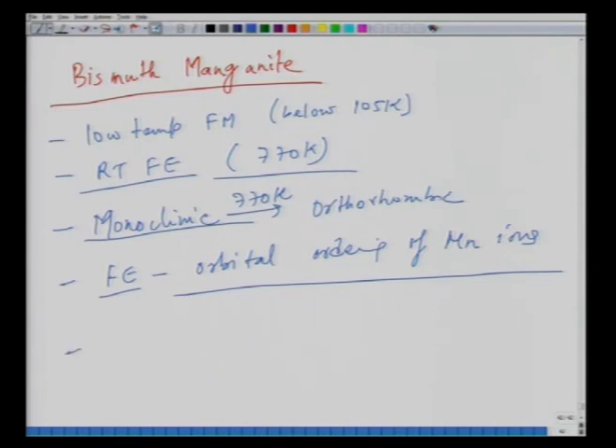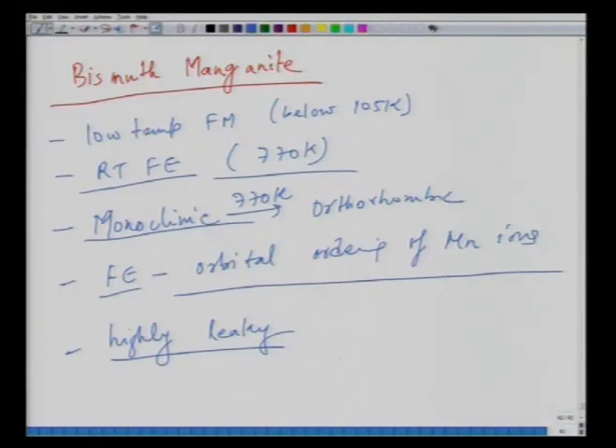The problem with this material is that it is highly leaky. So it's really difficult to make this material in a resistive form, because in order to have a ferroelectric effect you have to have high insulation, and this somehow has been a problem with this material. There are some studies recently which have reported high resistance in this material in the thin film form, but that again depends upon group to group and paper to paper. However, there are strategies which can be adopted to make this material more resistive.